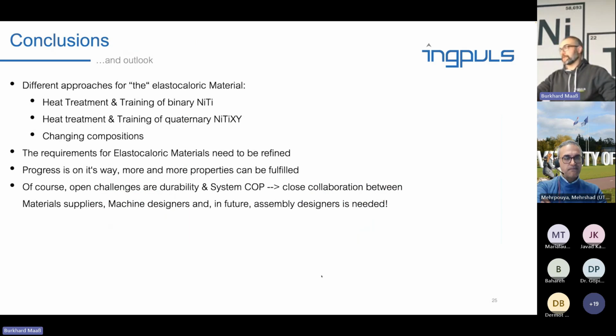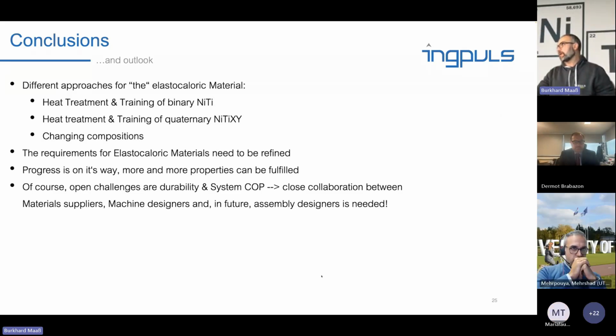So I already said, it's not just a material that you do in an alloy screening where you have a button melt and do a DSC. That's not enough. You need to be able to produce a semi-finished product out of that. Maybe a wire, maybe a strip, maybe a tube, maybe a bar, whatever the regenerator needs. So the heat treatment and training is very important. We almost never use first cycle data because we know that the material will change over cycles. We have changing compositions, we have changing parameters. Before we deliver out a spool of material or a batch of material, we want it to be trained.